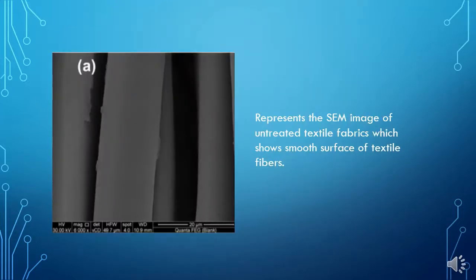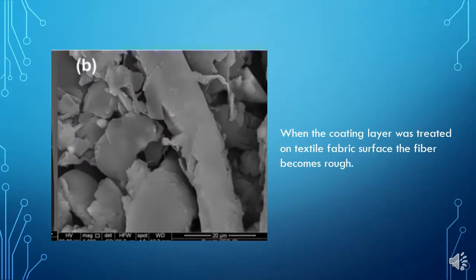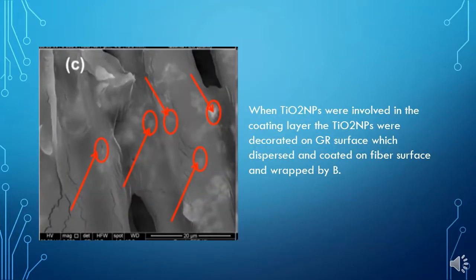This SEM image represents the untreated textile fabrics which shows smooth surface of textile fibers, while this image shows that when the coating layer was treated on textile fabric surface, the fiber becomes rough. This reflected the coating layer containing graphite wrapped by ammonium phosphate and the TMSD, and finally wrapped with the binder chains. This image shows when the nanoparticles were involved in the coating layer. The nanoparticles were decorated on the graphite surface, which dispersed and coated on fiber surface and wrapped by binder.